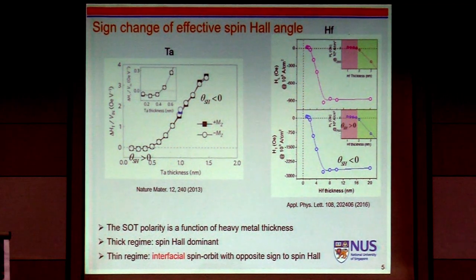The next question was, let's try some other materials. Is it really a general phenomenon, or is it only specific to this material? So we repeated many other materials, and we see very similar behavior. This is one example, hafnium. We started from 20 nanometers. We see conventional negative spin Hall. Then once we go below 6 nanometers, the amplitude decreases. This is typical spin Hall behavior.